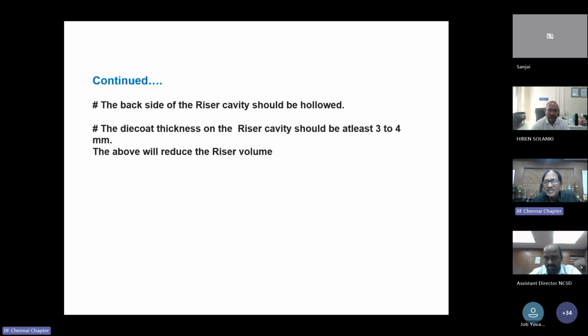The backside of the riser cavity should be made hollow, so that it will be thinner and get cooled not very quickly. The die coat thickness on the riser cavity should be at least 3 to 4 mm for retaining the heat. The above will reduce the riser volume.